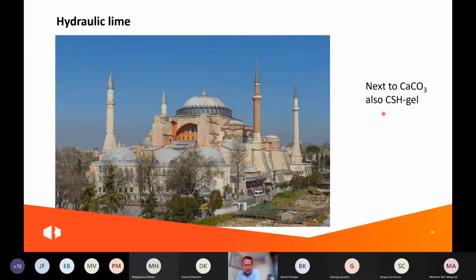The next step was hydraulic lime. You see here an old building. This is the Hagia Sophia, around 500 AD. But if you look closely at the mortar, then you will not only find limestone, hardened limestone, but you will also find CSH gel. So this was more or less already a hydraulic lime, or a combination of regular lime, pure lime I must say, and a pozzolan. Hydraulic lime was actually invented after 1800. It is lime combined with clay, or in the past it was probably, you can say, dirty lime. But if you combine it with clay, then you get a first component we have in modern cement.